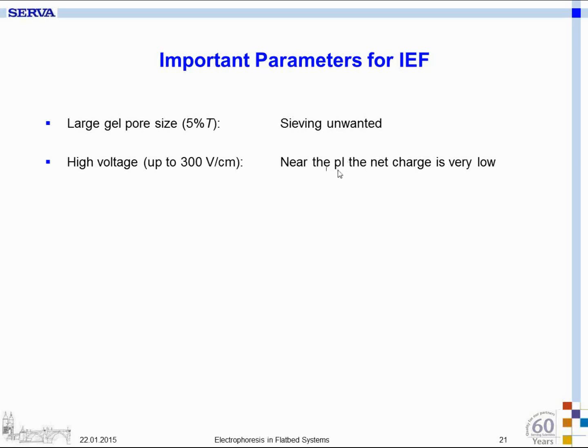You want to have high voltage, because close to the isoelectric point the net charge is very low. That means you need high electric field strength, up to 300 volts per centimeter, to get sharp focused bands. And that means for, like, say 10 centimeter separation distance, 3000 volts. You can do that on a horizontal gel. You never can do that on a vertical system. The temperature has to be very accurate because the pK values of the samples and of the carrier ampholytes, the pH gradient making reagents, are highly dependent on the temperature. So a few degrees up or down can cause quite different patterns and isoelectric bands.